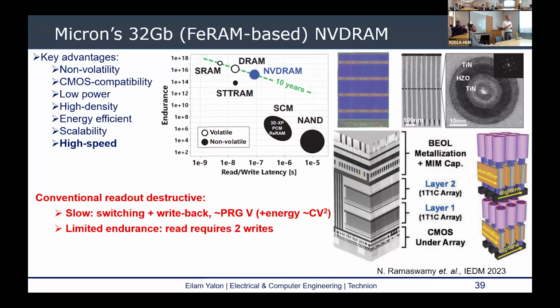But one of the main limitations remains that the readout of the polarization state is destructive. As we saw earlier, we need to switch the polarization to measure the polarization current to read the state of the transistor. And that means that every time we read, we have to write. So we need to apply higher voltages, which are programming voltages, and it takes longer time and energy because of this write-back process, and the endurance is limited. So even though the write endurance is fairly high compared to some of the other technologies, it's about 10 to the 11, 10 to the 12, it's still not infinite. And because of this destructive readout, the limited write endurance also limits the read endurance.